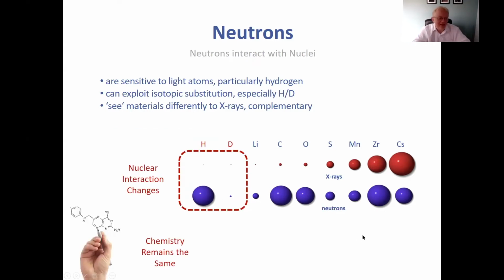Also, we can play funny games with isotopes. So deuterium has a very low scattering, whereas hydrogen has a very high scattering. But the types of scattering between these two are different. So hydrogen has an incoherent scatter, which means it loses a lot of energy, whereas deuterium has a coherent scatter. So if we want to do a crystallographic experiment where we're interested in the coherent scatter from the materials, the Bragg peaks, we can replace the hydrogen in our material with deuterium, and we'll get a strong signal for that.